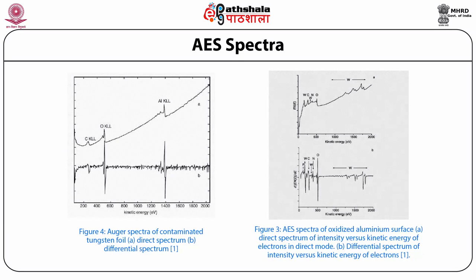The AES spectra. A typical AES spectrum is a plot of intensity versus kinetic energy. Or it is a plot of the first derivative of intensity versus the kinetic energy. The Auger peaks appear small against the background of the direct mode spectrum. This occurs because the signals from Auger electrons are relatively weak compared to the secondary electrons escaped from a solid surface. Electrons are either elastically or inelastically scattered when a primary beam strikes the material.